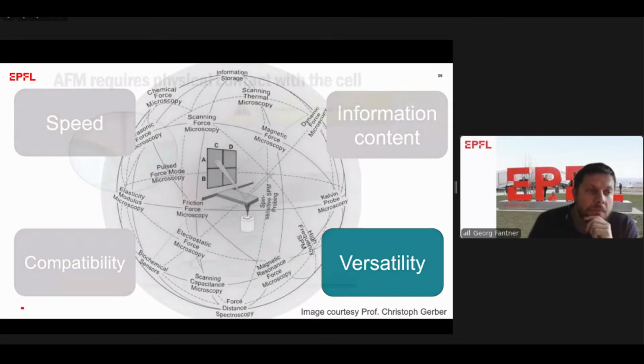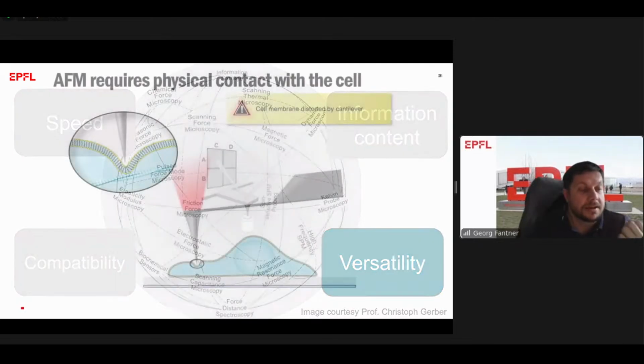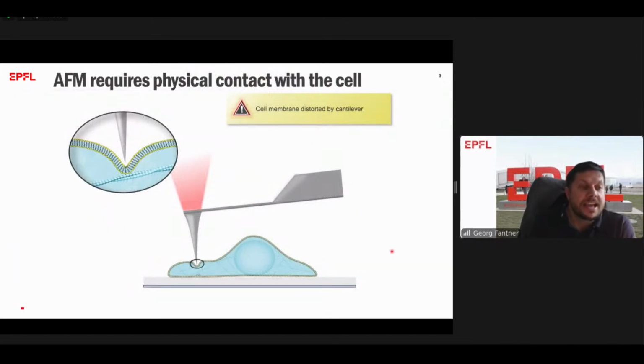Because the problem when we're trying to look at living samples, especially eukaryotic cells, is that we still have to interact physically with the sample. So we have a mechanical contact between the cantilever tip and the sample, and what we're actually measuring is not the surface of the cell, but the distorted surface of the cell. We're actually bending the membrane, so we're deforming it, and most of the times the cells don't like it, and we don't get a faithful reproduction of the cell surface.